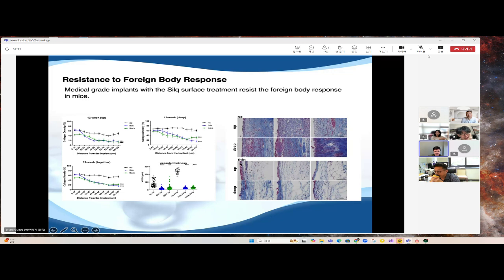With our treatment in mice for 3 months, 12 weeks, there's still a little bit of collagen right at the interface, right next to the device, but the tissue away from the initial capsule is completely healthy. And so we have more good indication here that we can resist fibrosis. And this might be valuable for your electrodes, to reduce their impedance over time.